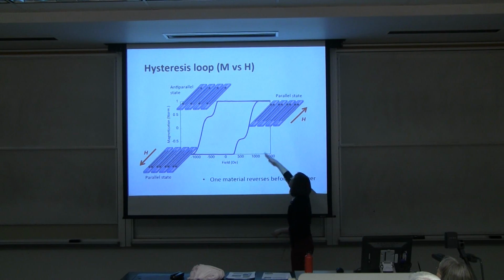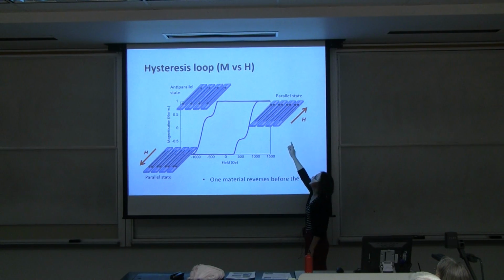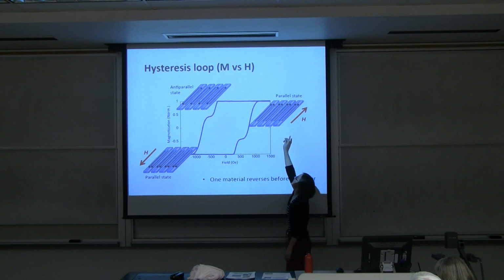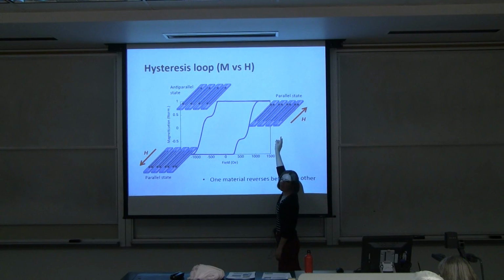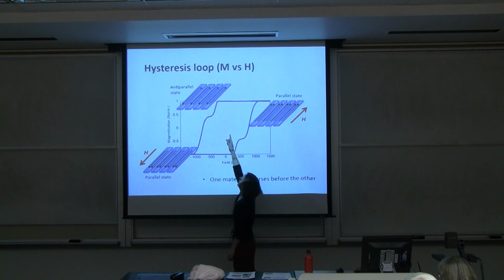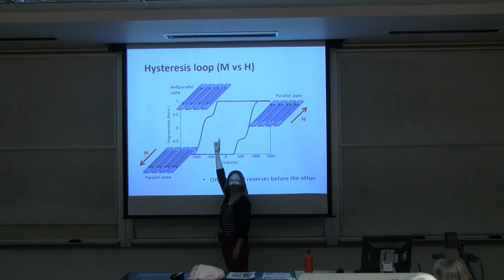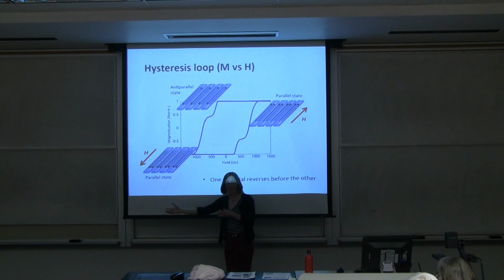So let's start off at high magnetic field. With high magnetic fields we have the stripes completely saturated, or all the magnetisation lined up along the stripe direction and along the magnetic field direction. And now we're going to reduce this magnetic field strength. And we go back to 0, and you can see there's actually no change. That's because the magnetisation likes to stay in that direction. It won't spontaneously flip unless we force it to.